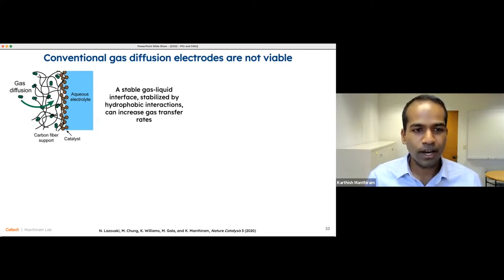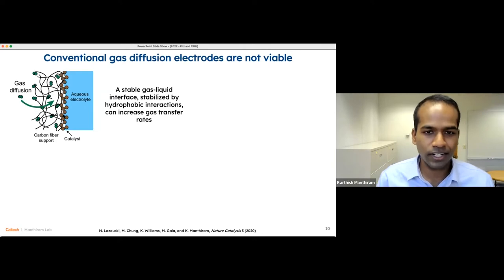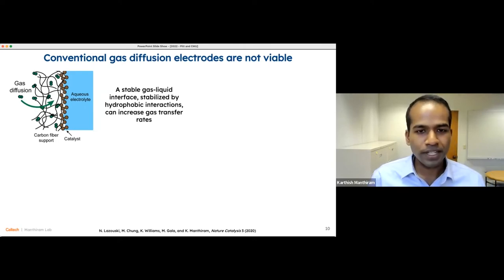This creates a nice clean boundary where one is able to contact the gas with the liquid electrolyte and with the solid catalysts that are here. There's also PTFE waterproofing, which helps even further in tuning the extent of aqueous electrolyte infiltration, and one can really tune that wetting to get this boundary to fall at the right place.